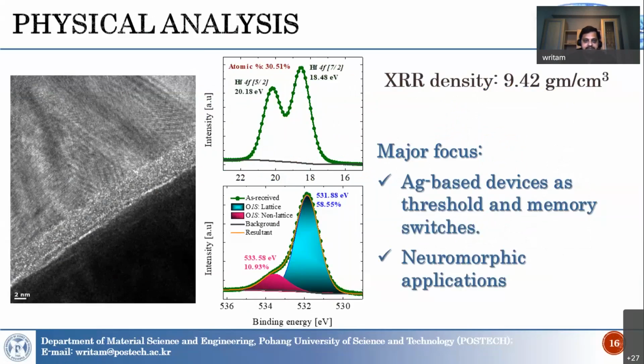Here is the physical analysis of the structure, and you can see we have a very clean structure. This is the bottom electrode, this is the 4 nanometer hafnium oxide, and this is the silver layer. The density of the hafnium oxide is around 9.42 grams per centimeter cube, and the composition was 1 to 1.9, so it was a non-stoichiometric structure.